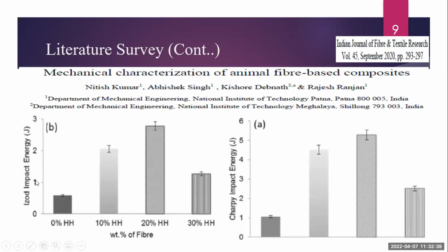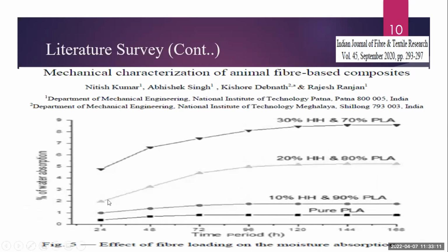Also, they tested impact using the Izod impact test technique, and they found that the sample of 20% horsehair with 80% polylactic acid gives the best results. So what we can conclude is that if we mix 20% fiber by weight percentage into 80% polymer, then it can give good results. We can optimize these mixing ratios through these results.